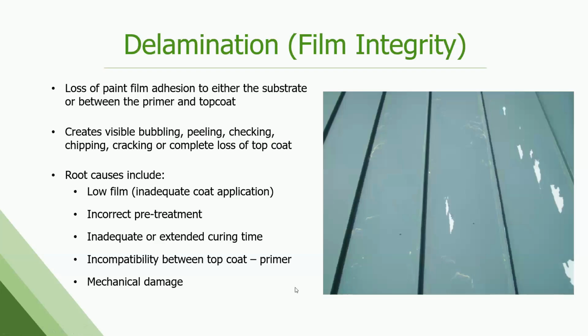Delamination. This is a tough one. Why is the paint coming off? And unfortunately, I've listed 5 possible root causes. There's actually about 400 root causes for this. It's a tough one to investigate. But this is a loss of paint, either top coat to primer or the entire paint system, including primer, coming off the metal underneath. Maybe bubbling, peeling, it might be chipping or cracking.